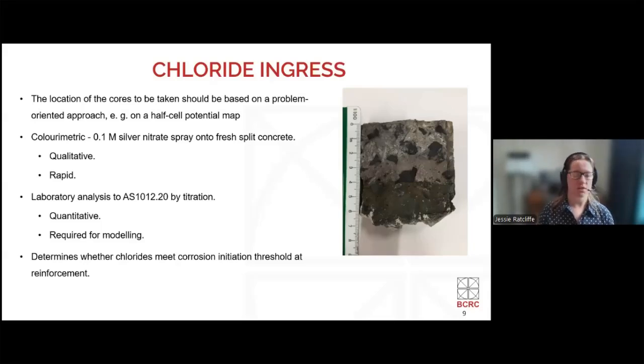We can test using a silver nitrate solution sprayed onto the fresh concrete and exposed to UV light. The color change produces this blue-gray discoloration at the top, where we have chloride ions, and then leaves a dark brown color where it's non-chlorinated. This core also has a pheno spray applied, which is why we get this Neapolitan effect, because we're doing both tests.